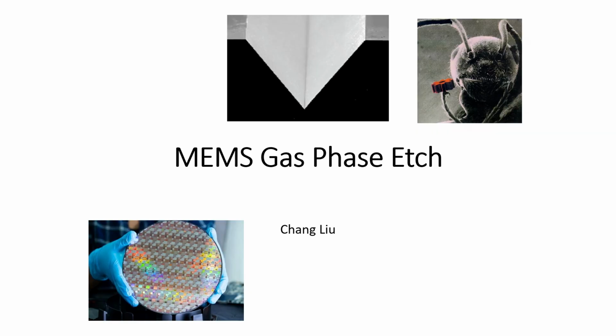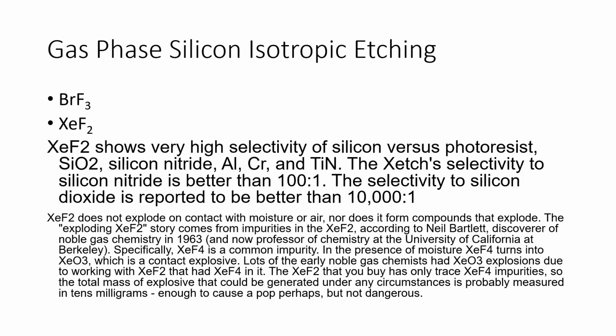Welcome back to Introduction to MEMS. We will be talking about gas phase etch of silicon. In the extreme case, silicon can be used as a sacrificial layer material. The gases that can etch silicon relatively fast are bromine trifluoride and xenon difluoride. Those two etch silicon without attacking photoresist, silicon oxide, silicon nitride, aluminum, chrome, and titanium nitride. So it is a fairly good material.